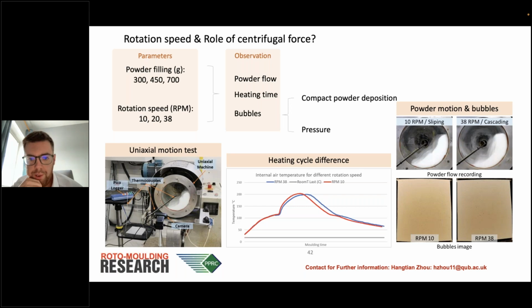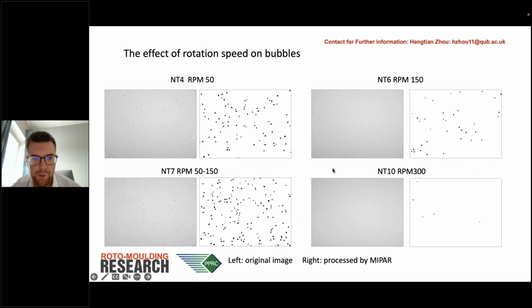At the same time as doing that, he's also looking at how does the speed affect the moldings. So he's using a uniaxial machine to try and simplify his experiments, and he's making comparisons between, in this case, 10 RPM and 38 RPM, the speed of rotation of the mold itself. And some of his early work has indicated that the rotation speed does have an effect on the bubbles, and you can see that increasing from 50 to 300 rotations per minute dramatically reduces the amount of bubbles that are present in the mold taken from an image at the same point in the cycle.